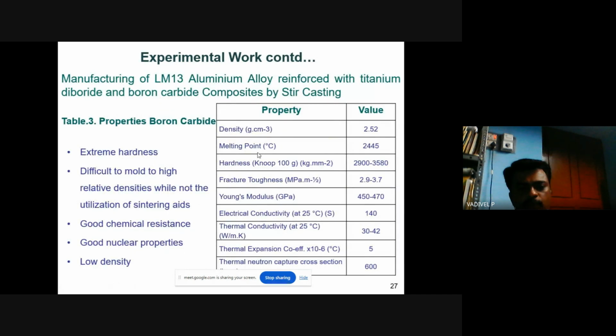And the physical properties of the boron carbide, the ceramic we have used, is the boron carbide. Why we have selected this boron carbide is because of its properties: extreme hardness, and it is difficult to mold to high relative densities without the utilization of sintering aids. It has good chemical resistance, good nuclear properties, and low density. So because of these very important properties, we have chosen the boron carbide.